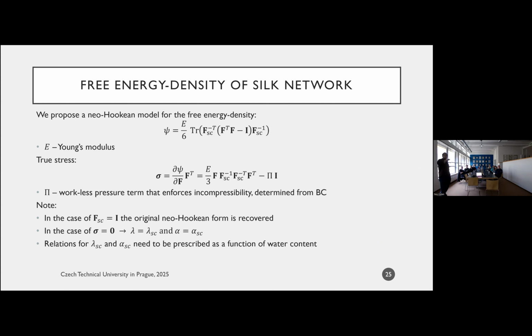And so what we've done is we've taken some motivation from liquid crystal elastomers, and we said, let's look at an energy density function that looks like this, right? So this looks like the neo-Hookean. The twist here is that we're changing the traction-free state. And if you do this, you can define the stress. So that's what the stress looks like. Pi here is the workless pressure term to enforce incompressibility, because we have to enforce incompressibility somehow.